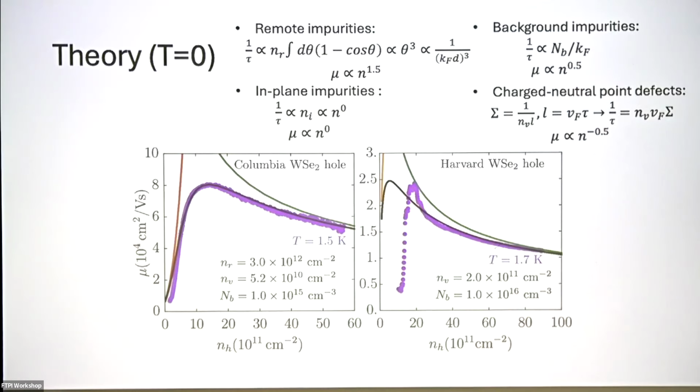I looked at that paper and summarized its result in 2 lines. So those beyond-Born-approximation results can actually be captured not from quantum mechanics, but from classical mechanics. That's one of the greatest things Boris taught me. So for vacancy defect scattering, if you think of it classically, the scattering cross section is a constant. It's just limited by the size of the point defect.